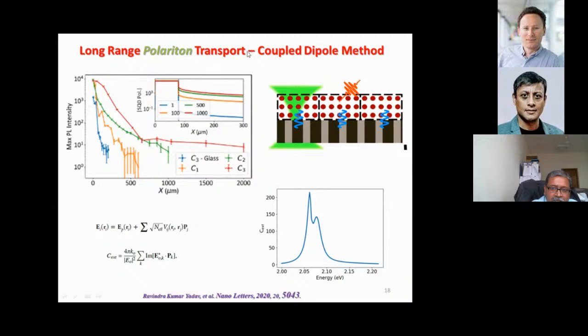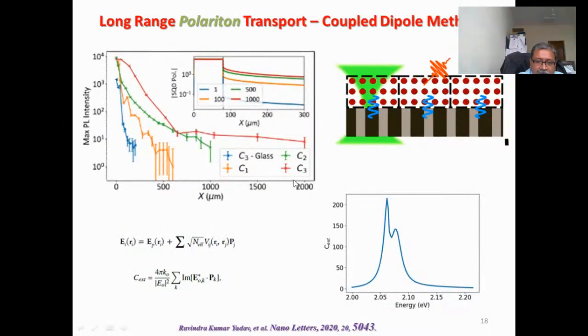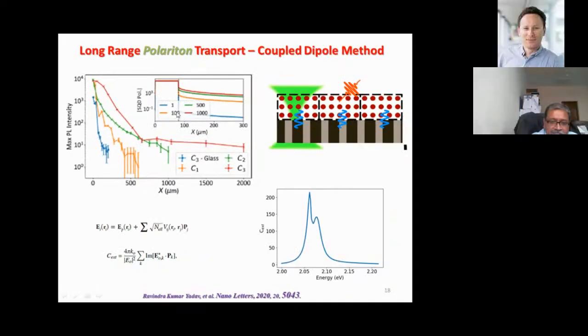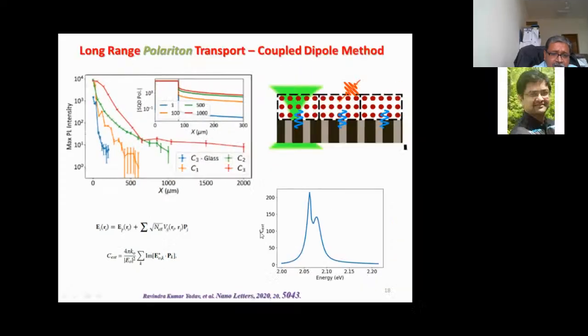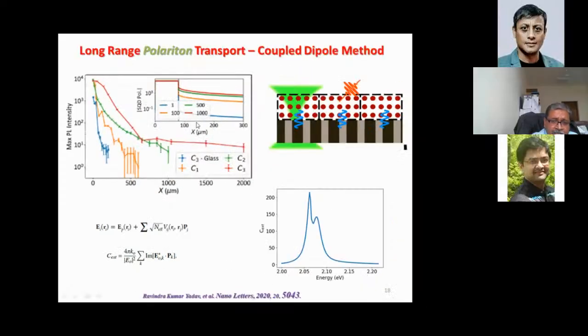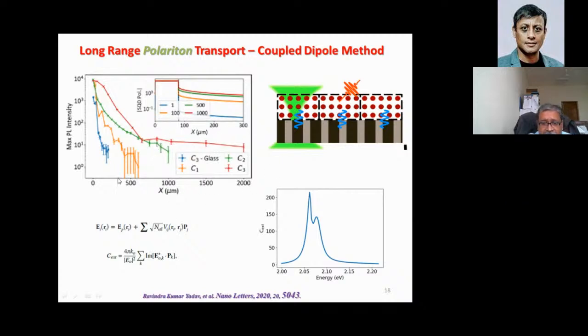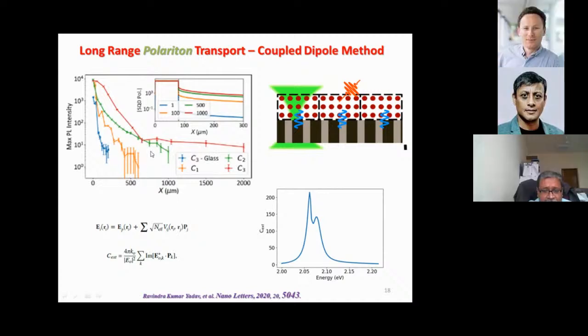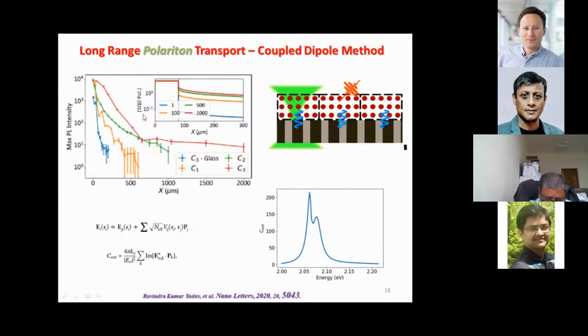So this was modeled using the coupled dipole method, not in an exact distance dependence, but as we can see here, when we vary the concentration, we see this kind of decay away from the excitation region, basically showing that it is scaling with the concentration as we see in experiment. So this is something quite fascinating, and there can be many different directions or applications in which you can further explore this behavior.